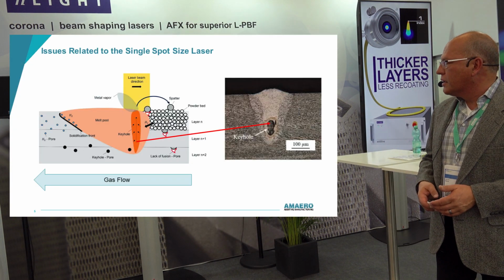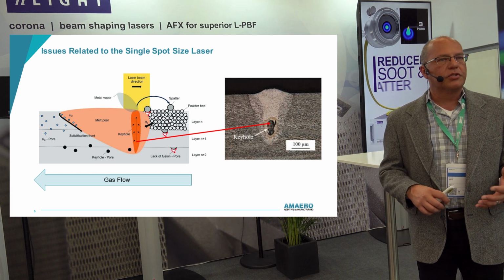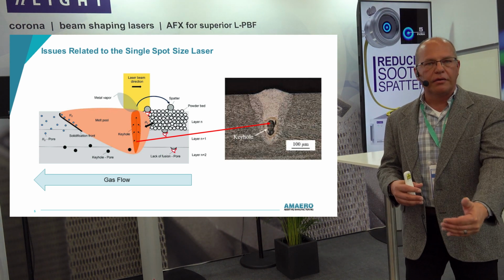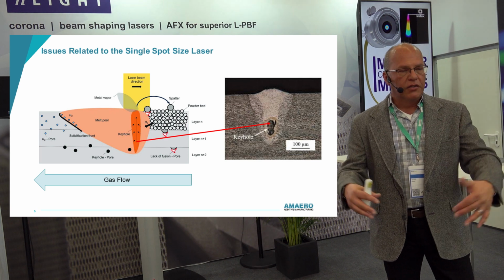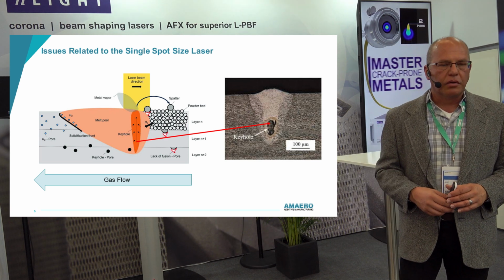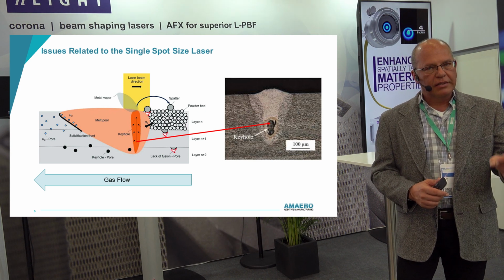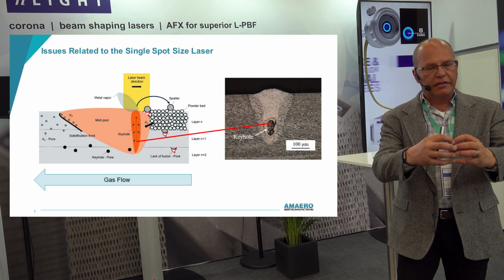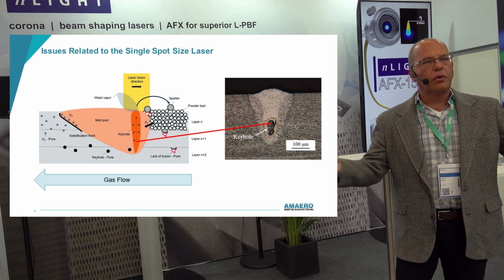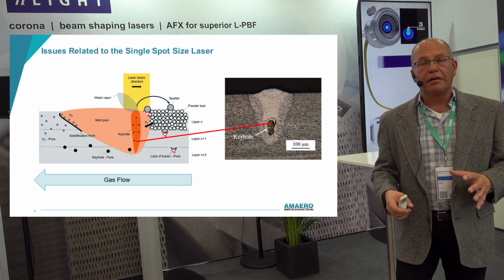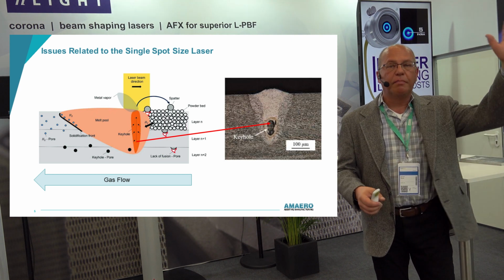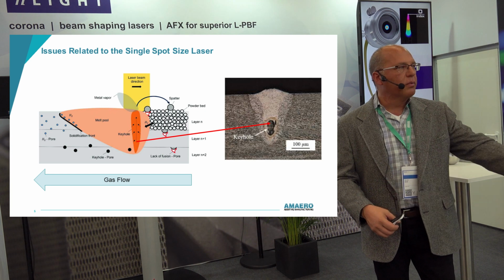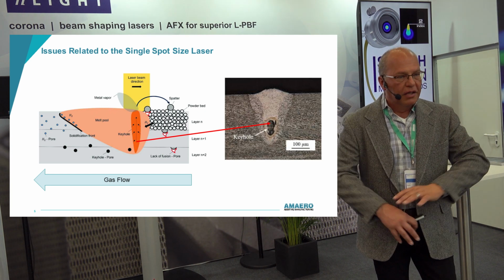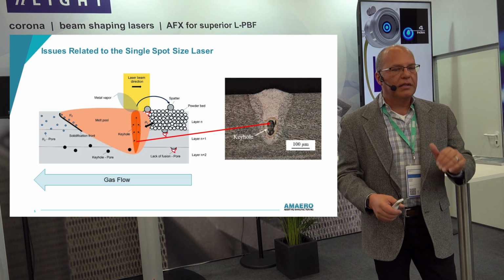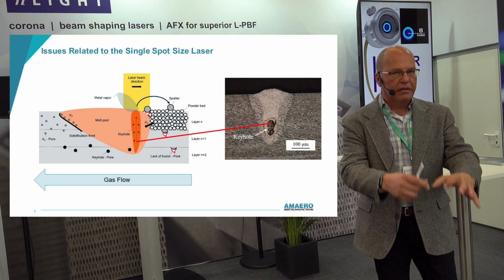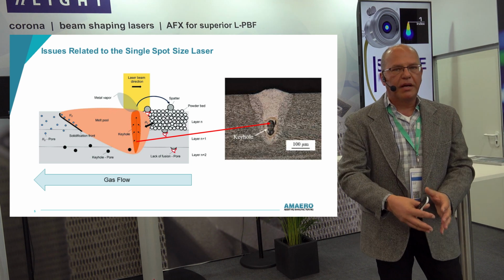Wayne King did a lot of seminal research in what's really happening when the laser hits the powder, and we saw some earlier presentations today as his work has been taken on by a lot of researchers around the world. We used to think that the laser hit the powder, heated the powder, melted the powder, consolidated it, and then the melt pool would draw in additional powder around it. Turns out the beam hits the powder and pretty much blows the powder out of its way. Imagine the floor was covered in ping pong balls and we hit it with a fire hose. All the balls scatter. The laser is really engaging the substrate below the powder, melting that, and then drawing a bunch of powder in around it.